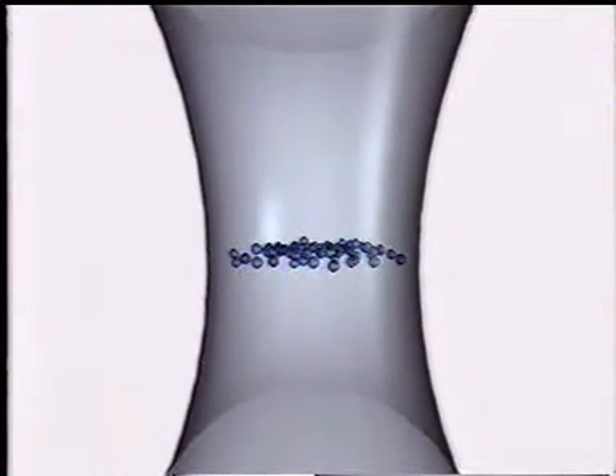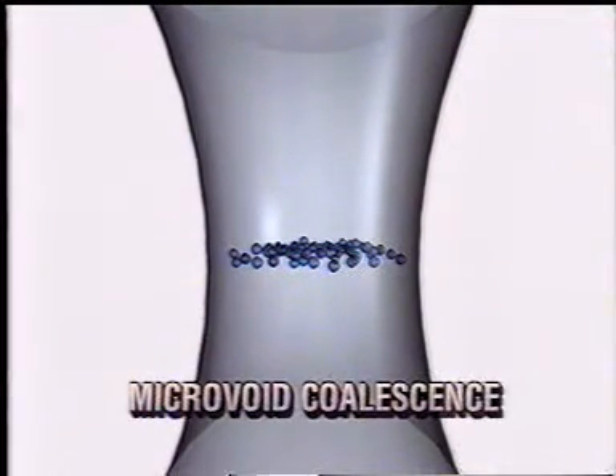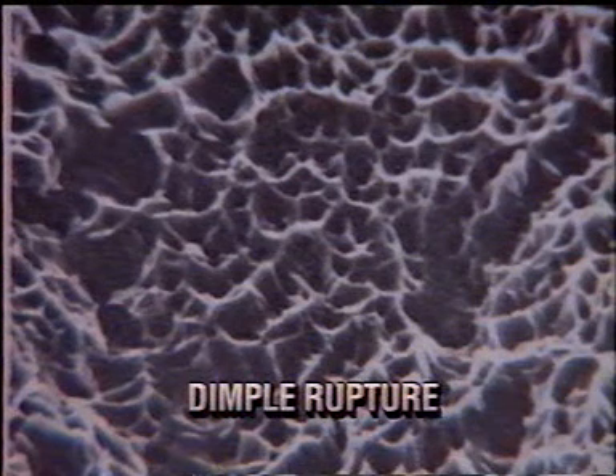When overload is the principal cause of ductile fracture, most common structural alloys fail by a process known as microvoid coalescence. Tiny cavities form at regions of localized strain, such as that associated with foreign particles, inclusions, and grain boundaries. As the strain in the material increases, these microvoids grow in size and begin to join together or coalesce. Eventually, these coalescing microvoids join to form a continuous fracture surface known as dimple rupture.